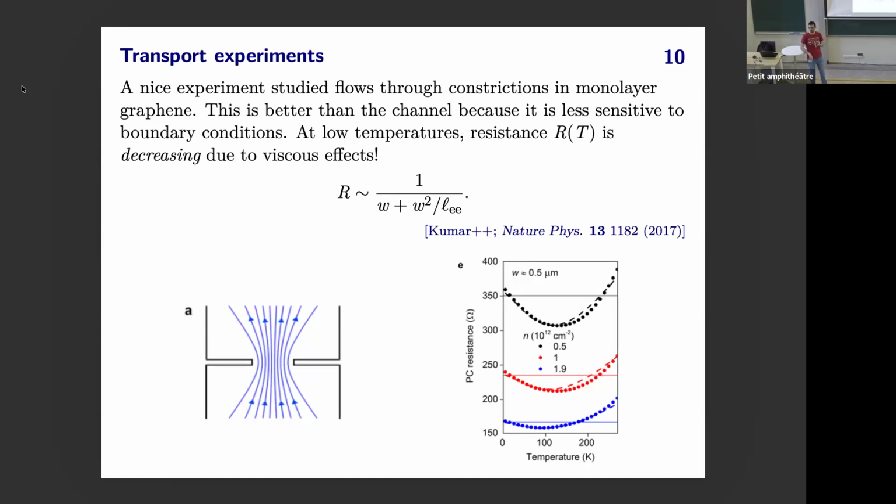You're about to say what the horizontal lines are. Those are the ballistic transport. I think I mentioned before, but I can say again. This solid line is basically a quantitative prediction for what's called Sharvin resistance, which is the ballistic resistance. So the fact that it dips below that means electrons are scattering off each other. That's right. The fact that you get a resistance smaller than that means that interactions are helping the fluid move more efficiently through this constriction. Water. Yeah. Okay.